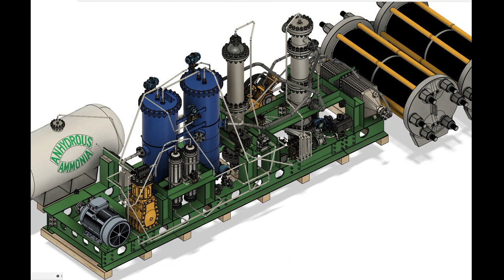Space velocities and the factors that determine their selection. For industrial scale plants, space velocity is largely a function of the pressure. The common space velocity of a low-pressure loop is set at 5,000 to 10,000 per hour, a medium-pressure loop at 15,000 to 30,000 per hour, and a high-pressure loop as high as 60,000 per hour. For our smaller-scale plant, we have chosen moderate to high pressures, thus reasonably high space velocity, bearing a high catalyst productivity. One of the principal advantages of higher pressure systems, namely 30 megapascals or more, is the ability to more easily separate the synthesis gas through condensing the reacted product.